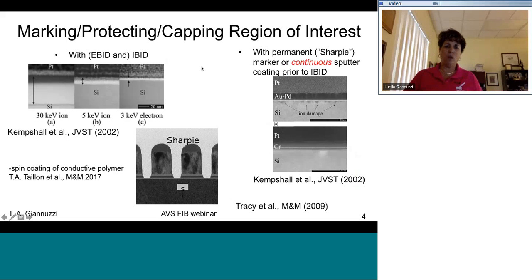As I mentioned earlier, if you want to FIB mill across a region of interest that's right on the surface that can be damaged with the FIB, there's a number of ways that you can protect it. One is with electron beam deposition prior to FIB deposition. One is with a coating, but make sure it's a continuous coating. The other thing that you can do is to use a Sharpie pen, which is basically just conductive carbon particles inside of a polymer and a solvent. This is your permanent ink marker, for example. Or you can also spin coat conductive polymers on top of the region of interest. So there's a number of things that you can do to protect your sample prior to FIB milling.